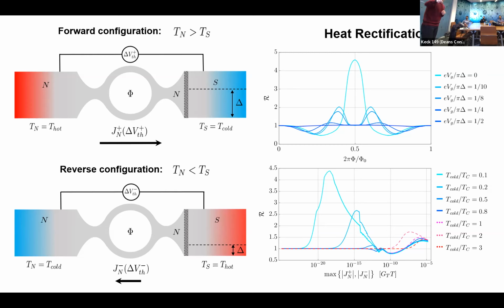However, you can see here in the bottom right corner that for almost every value of the temperature, we can get a rectification of the order of 1.5, meaning a 50% rectification, which is still good, and which corresponds to a value of the heat current of the order of a few hundreds of nanowatts. If you keep in mind that in standard experiments you can have access to picowatts, this means we have a five orders of magnitude difference, which is sizable and that you can measure.